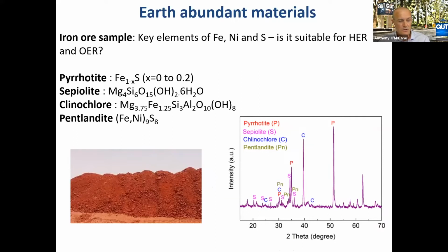The type of iron ore that we had here consists of these particular phases. What you'll notice is that we obviously have a lot of iron, but we also have nickel in there, which is a known catalyst for oxygen evolution and also hydrogen evolution. So we thought, okay, we have a lot of ingredients here which could make this an active catalyst for both reactions.